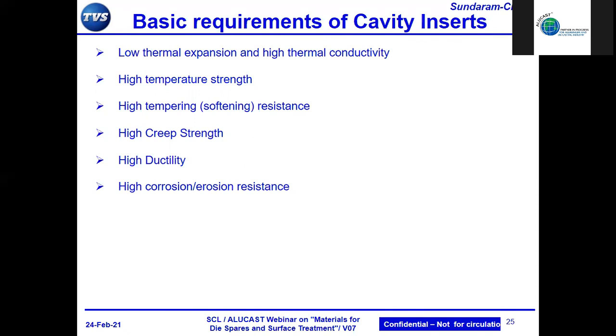Going forward, there will be demand for parts that require high ductility in these parts that we are producing through die casting. In such parts, iron content is expected to be much lower to enable the ductility. That becomes a challenge when we design and select materials, where in this case of yours you have a thick mass and you have soldering. When you have a much lower iron content, a lower thickness material also starts getting soldering. So the tendency of soldering gets more and more as you reduce the iron content. That is where I was coming from.